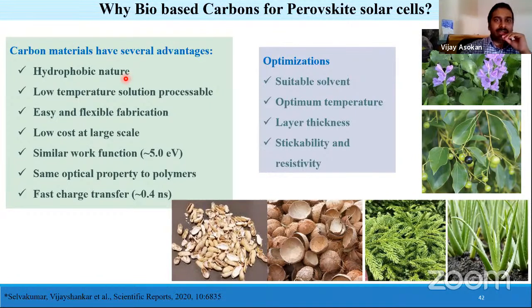It is hydrophobic in nature. If you remember from the degradation slide, those reactions of water or moisture into the hole transport layer cause corrosion even up to the perovskite layer. So we need to consider the hydrophobic nature of the material introduced as the hole transport layer. It can be low temperature solution processable, with easy and flexible fabrication, and low cost at larger scale, with similar work function compared to other HTL materials, the same optical property as polymers, and fast charge transfer.